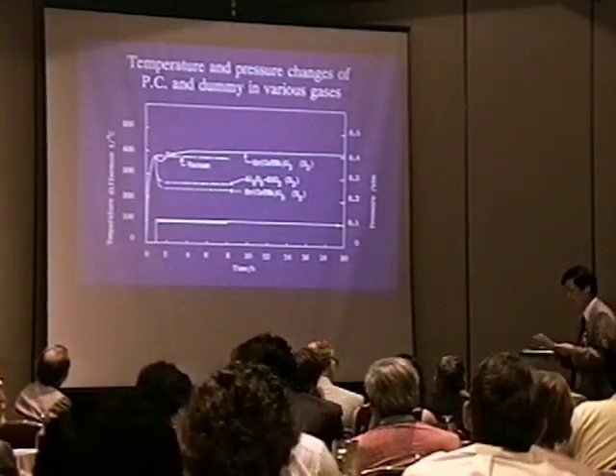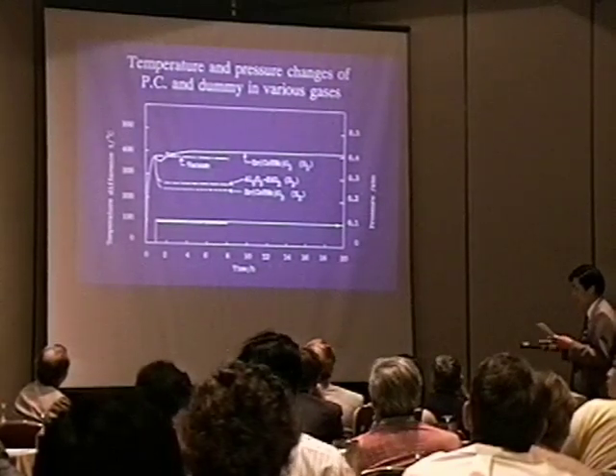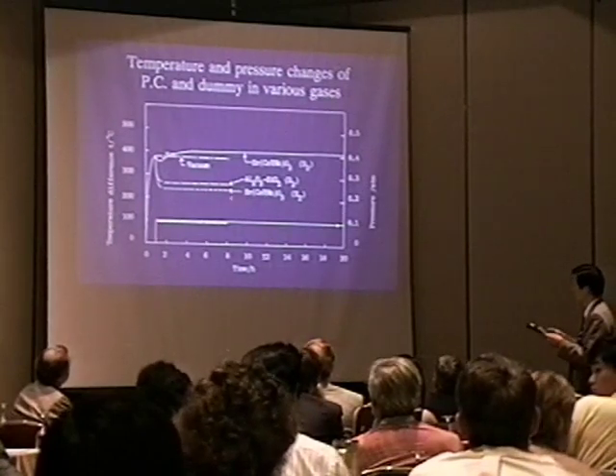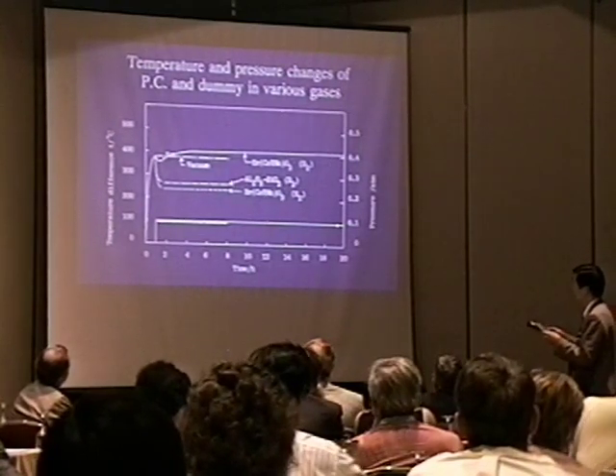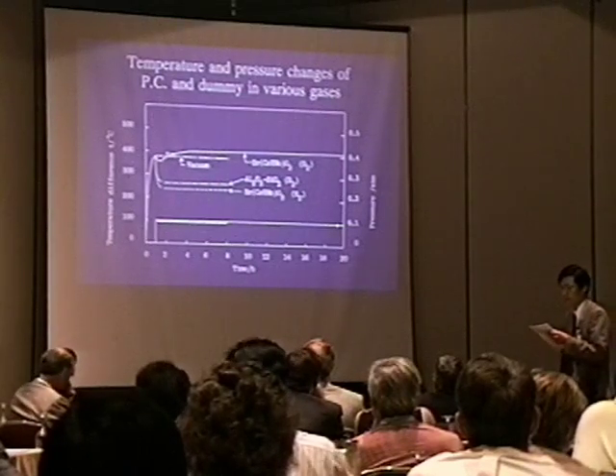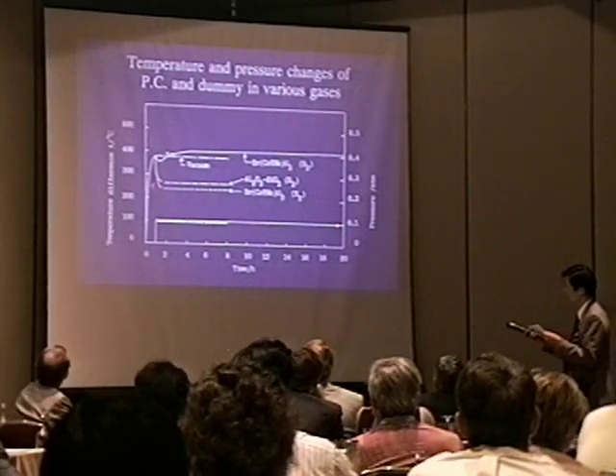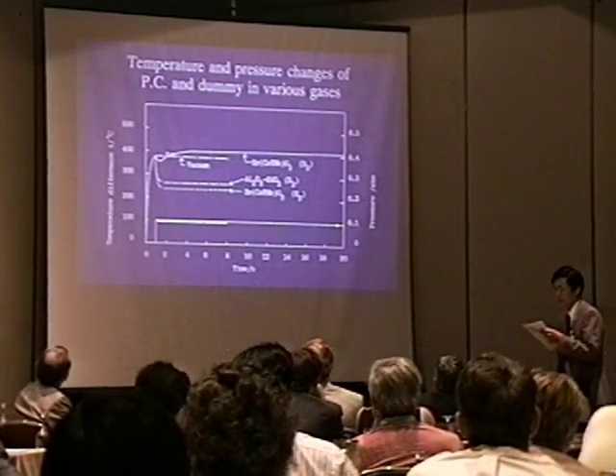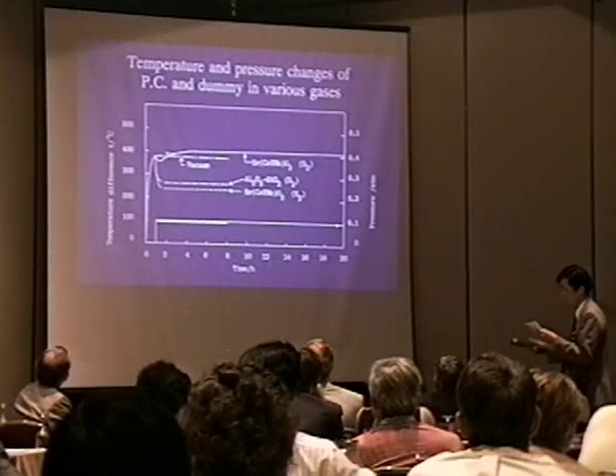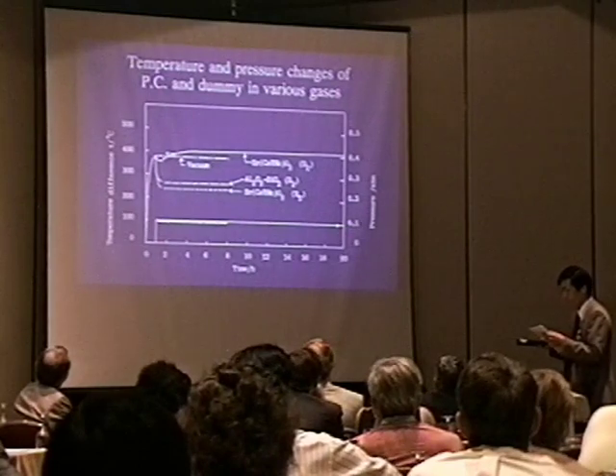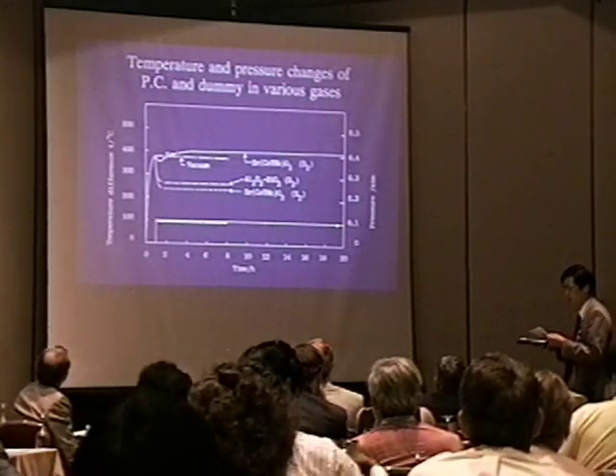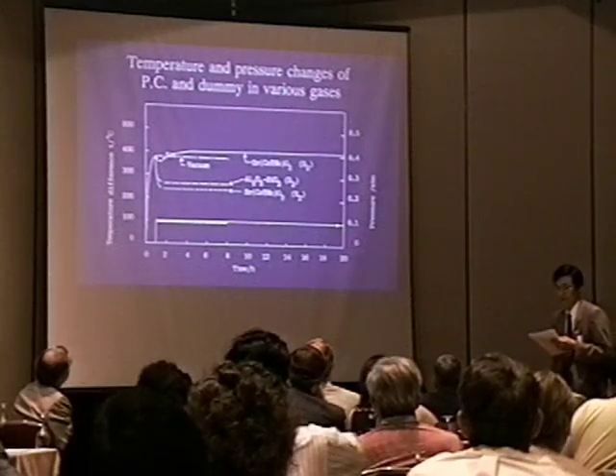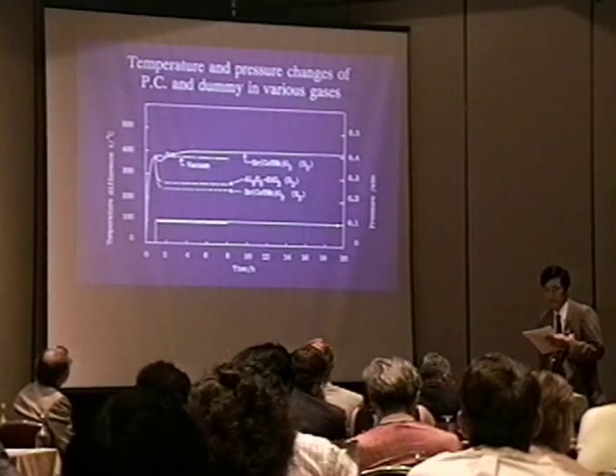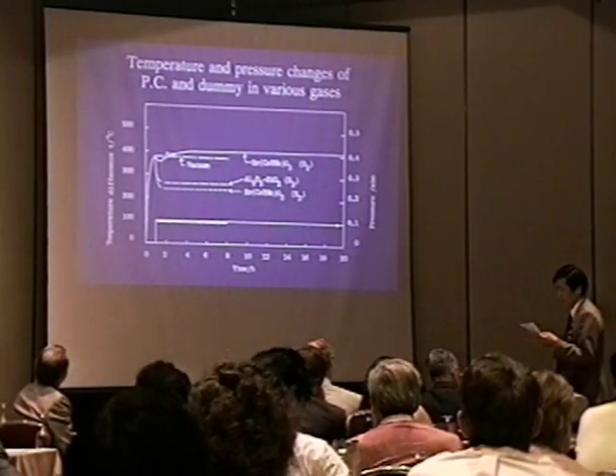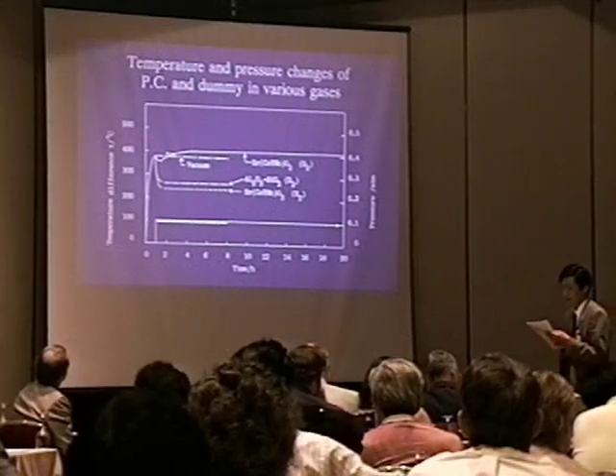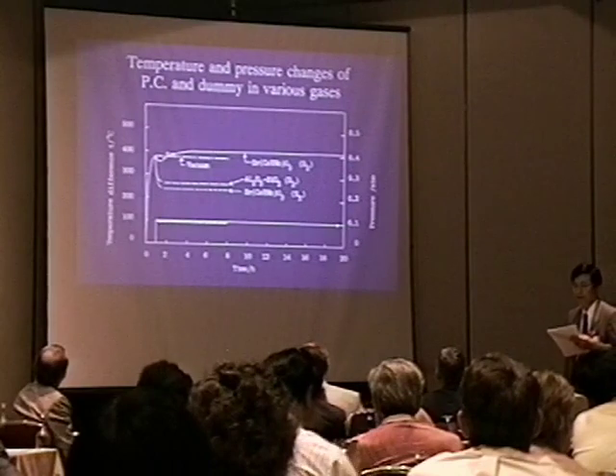In the other experiment in hydrogen gas, with the same type of sample, this dotted curve, or dummy samples in deuterium gas, broken curve, the temperature fell down to about 207 degrees centigrade within 1 hour, and stayed there afterward. This type of temperature fall should well be accounted for as due to increased heat loss caused by thermal conduction of hydrogen. A small difference recognized between deuterium and hydrogen gas is probably caused by a small difference in their thermal conductivity.